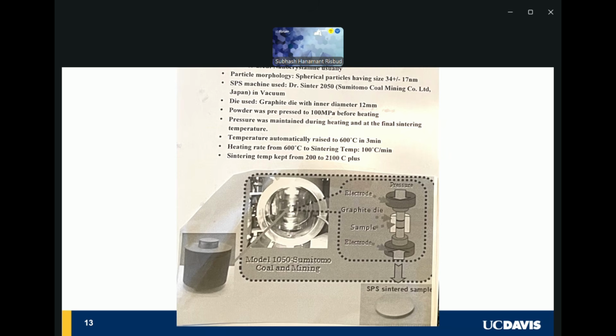But key to this process is not so much the pressing. Hot pressing does that too, so does hipping and all the other techniques. But here, the beauty of the technique is that the first step at room temperature essentially is an electrical pulse. So when the powder goes into the graphite die, you apply an electric pulse that's an on-off type of situation, and it goes on for maybe just a minute or two. So the powder first sees this on-off electric pulse for a short time, and then you heat this whole thing up to temperature. And often the graphite die is surrounded by graphoil sheet, so it's pretty much protected from any other exposure. You can put this under vacuum condition, or put argon or helium or other gases in it if you like. So that's kind of the typical arrangement for it. The Dr. Sinter machine uses a graphite die.